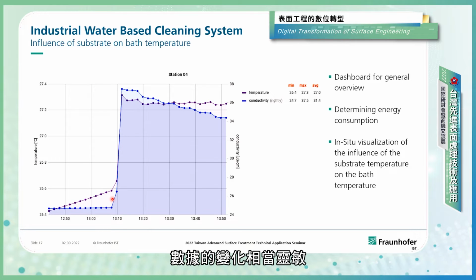And that's quite sensitive because this gives information on the cleaning agents, whether we have to recalibrate or add some cleaning agents, but it's also dependent on the temperature. So you can see directly the interaction between the baths in the process, and we get an in situ visualization of the influence of the substrate temperature of the bath on the bath temperature.